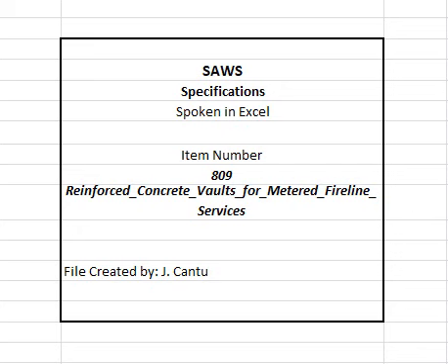6. Inspect, sample and test concrete in accordance with ASTM-C 94, Section 13, 14, and 15, and ACI 311-5R. 7. Test cores, conform to ASTM-C 42. 8. Testing high early strength concrete. When Type 3 cement is used in concrete, specified 7-day and 28-day compressive strengths shall be applicable at 3 and